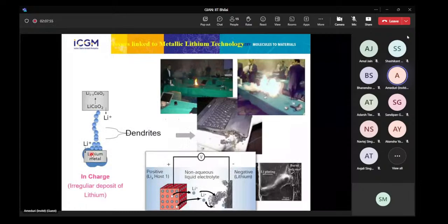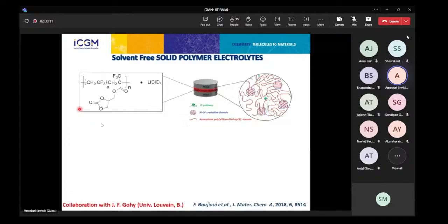So the issue is that you can have a lithium bridge between the two electrodes, a lithium solid, which makes a short circuit and induces very severe drawbacks. And in order to avoid that, it's necessary to have some solid polymer electrolyte and to have very good adhesion between the electrodes.